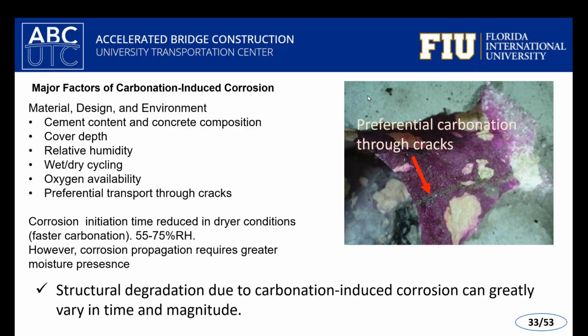So in dry periods, for example, you can have fast diffusion of CO2 and oxygen, but in wet cycles, you allow that coupling of those electrochemical reactions to occur to promote that loss of metal. If you were to have relative humidity around 55 to 75%, you would tend to have faster carbonation rates through the concrete. But again, we mentioned that for the corrosion rates to occur, you need that coupling, you need that moisture there. So the picture on the right-hand side shows something interesting, to me at least.